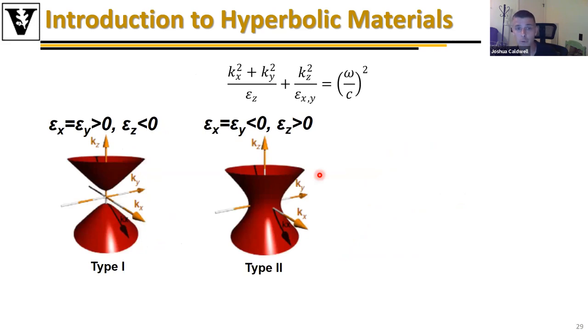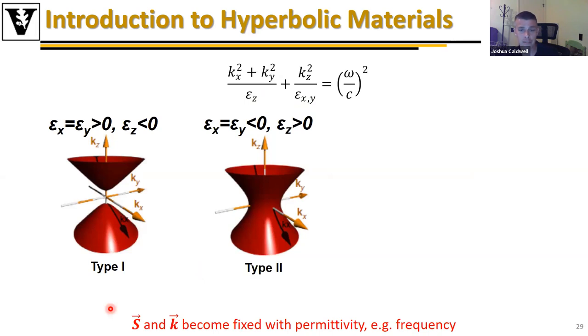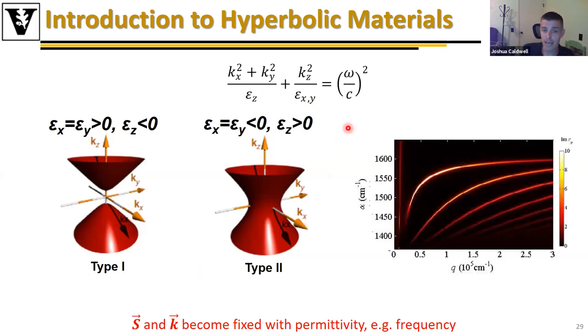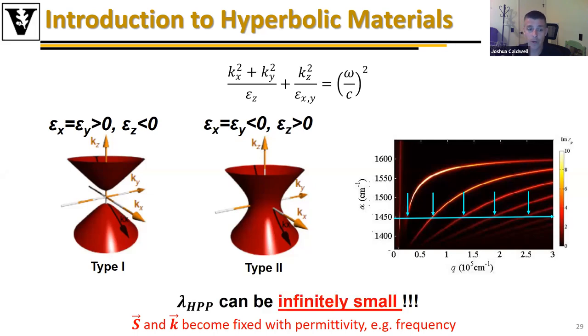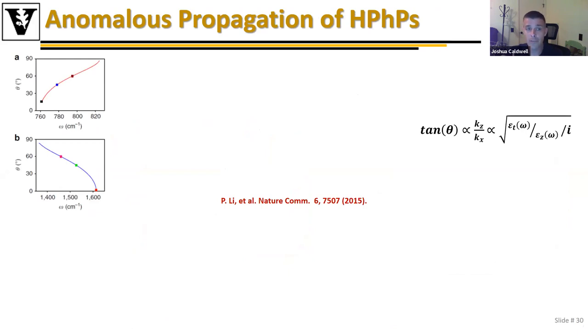One of the interesting aspects of these hyperbolic materials, and also where they get their name, is that if one of these permittivities is negative while the other is positive, you end up with an open hyperboloid shape for the isofrequency contour. So to visualize what that means, I can support arbitrarily large k, but the direction of propagation is fixed, because the pointing vector is going to be perpendicular, or tangential, to this isofrequency surface. So I end up with a dispersion for a finite thickness slab that looks like this, right? Where not only do I have that original fundamental mode, but I have all these additional higher order modes that occur. So at any given frequency, I can support a broad variety of different momentum modes with smaller and smaller wavelength, right?